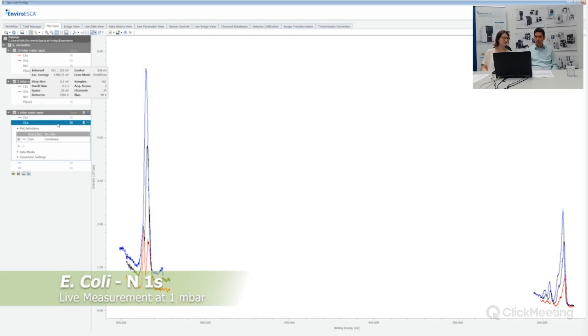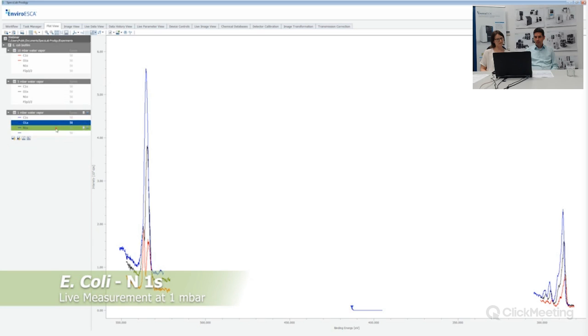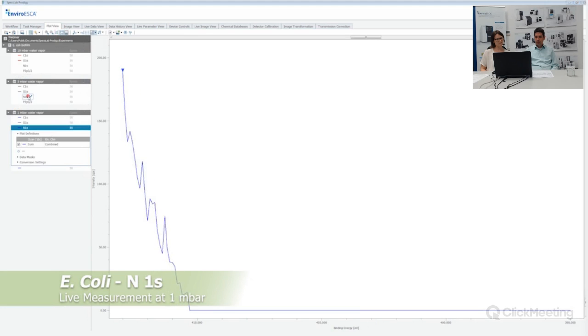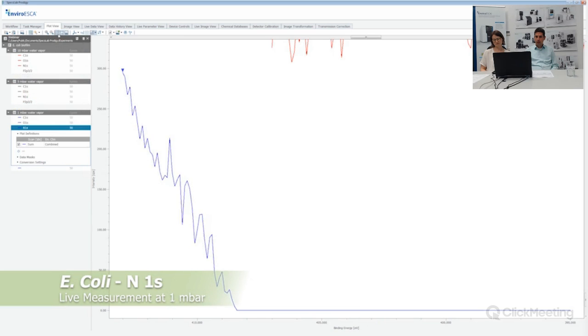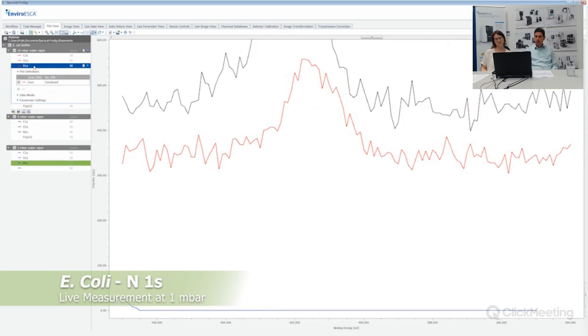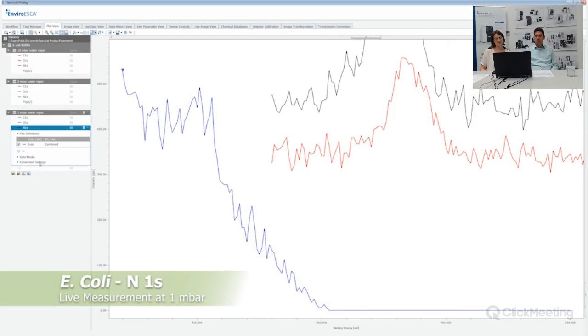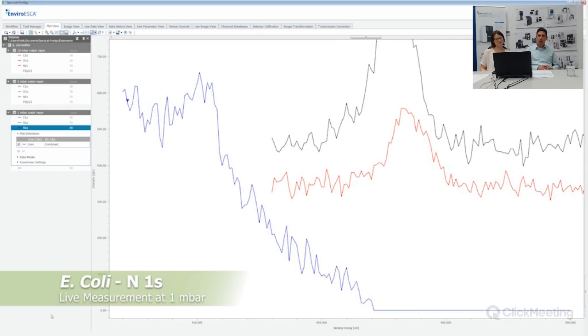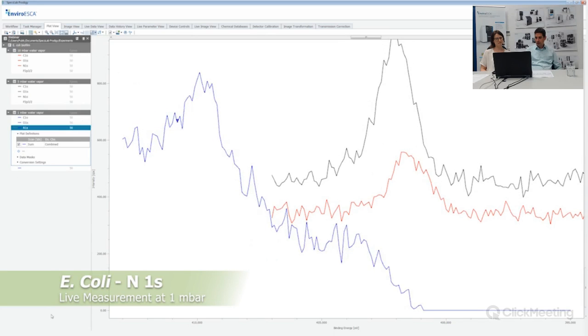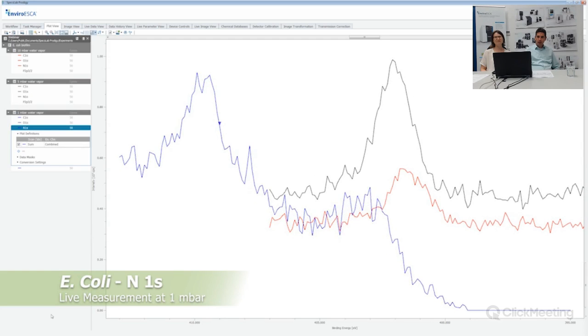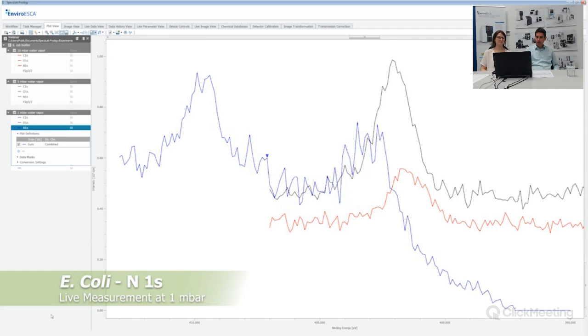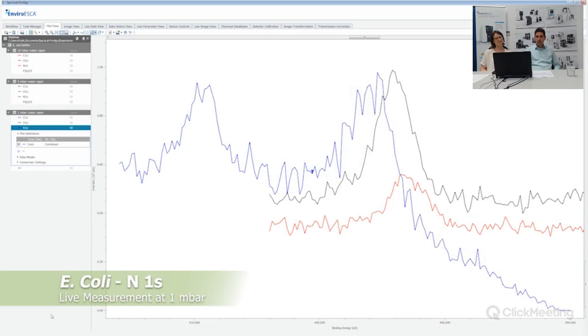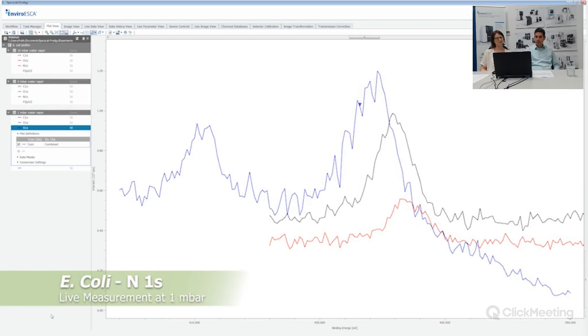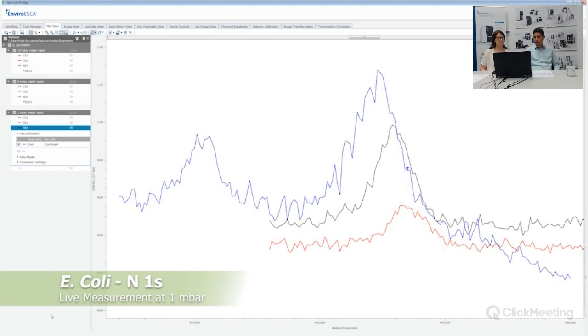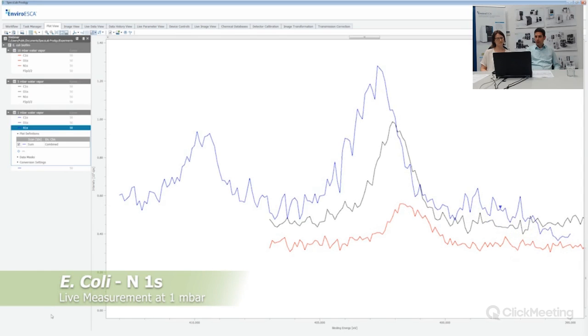Then we are at the nitrogen peak. So now you see the nitrogen starting, compared to the other two before. And now you will realize that there is a second peak in the nitrogen region, in the area around 409 or 410 eV, which is caused by residual nitrogen gas in the system. And then you see the main peak from the surface of the bacterial film itself, which is now much more intense than the other ones at 5 and 1 millibar. And this maybe could help to differentiate different nitrogen species in a not so intense nitrogen peak.